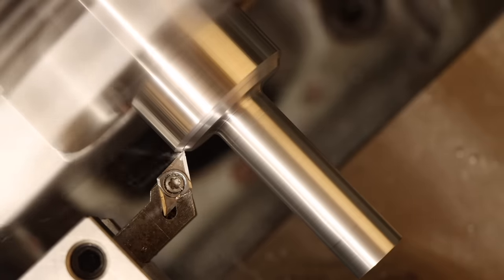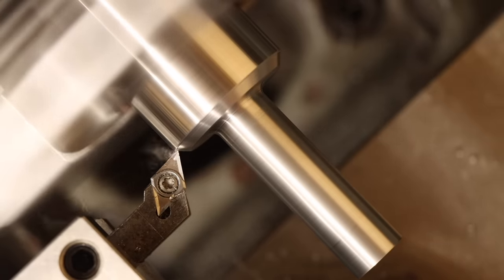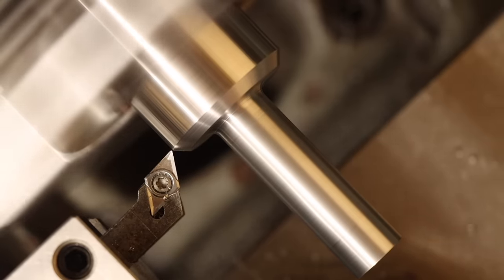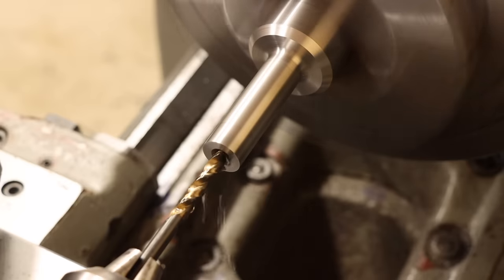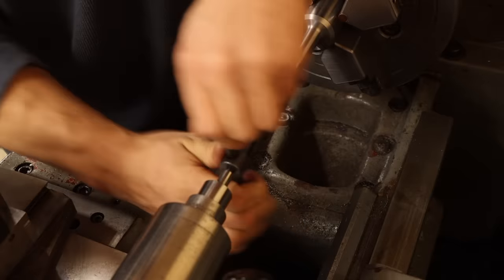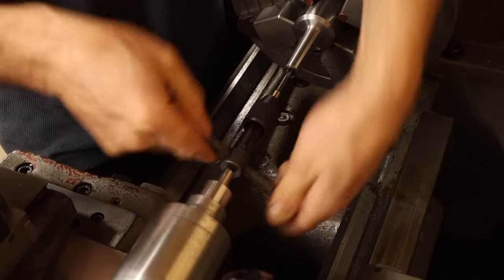As I hope has become obvious by now from my continued emphasis, concentricity is critical here too. So I've removed as much material as possible on both the inside and outside. If things are going to warp, I want them to do so before I cut the final taper, not after.